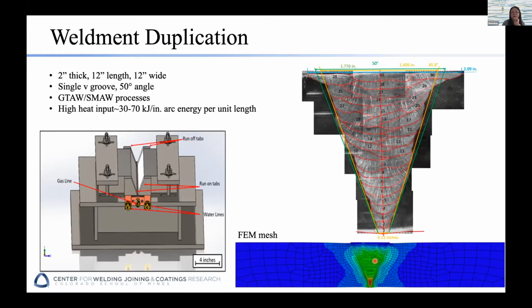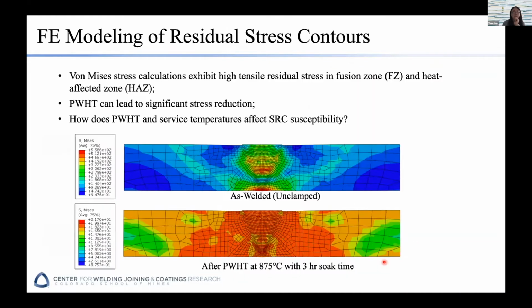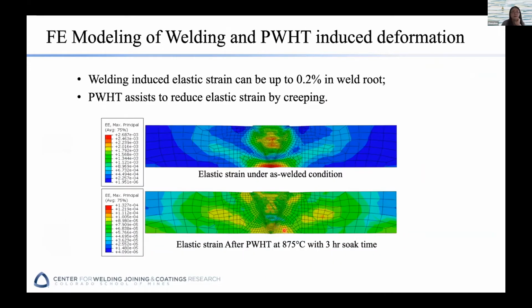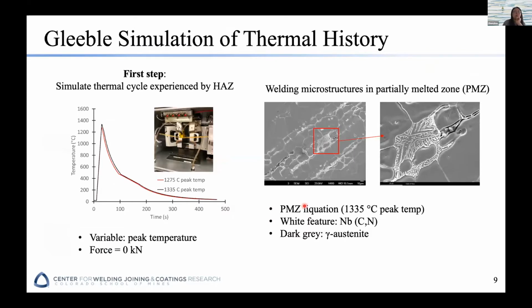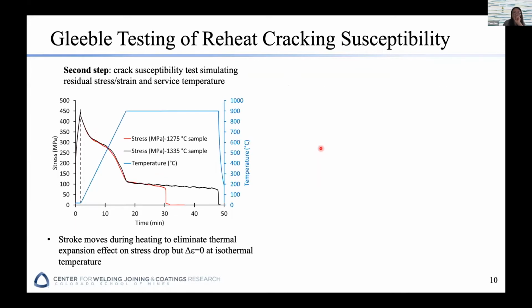Okay, and we also created a finite element simulation trying to simulate this welding process. Those two images show the residual stress distribution after welding. Okay, and we also have how much deformation is introduced into the material because of welding. And this one shows we simulated the thermal history during the welding process and see what the microstructure looks like. So you can see all those liquid films start to form, wetting the grain boundaries.